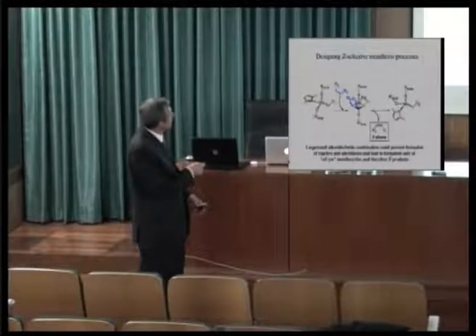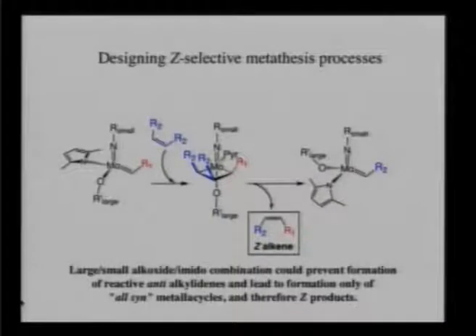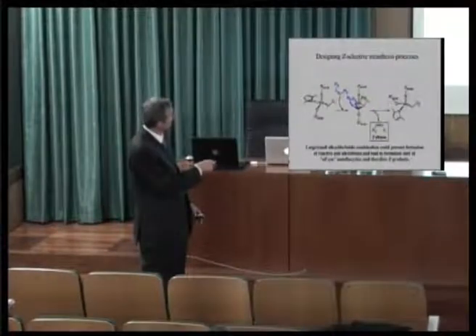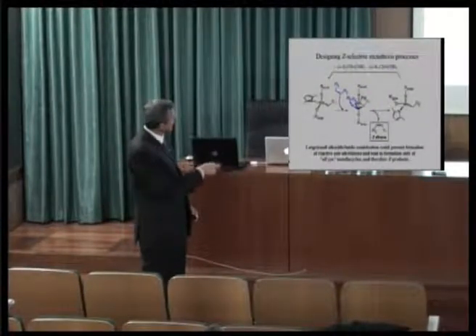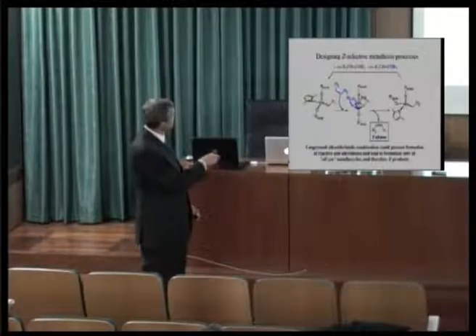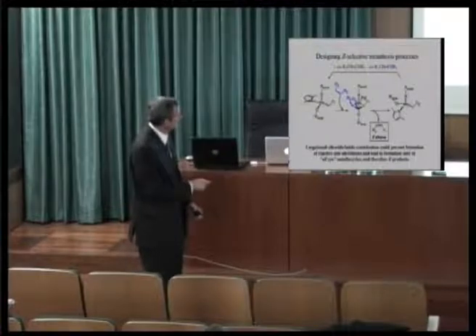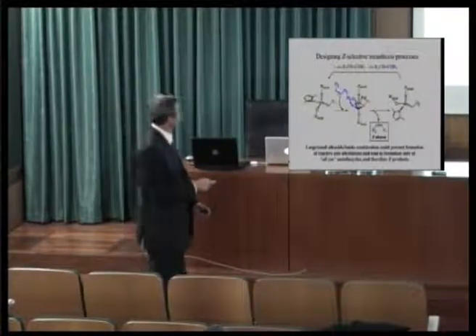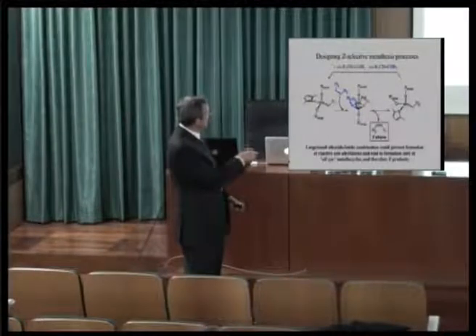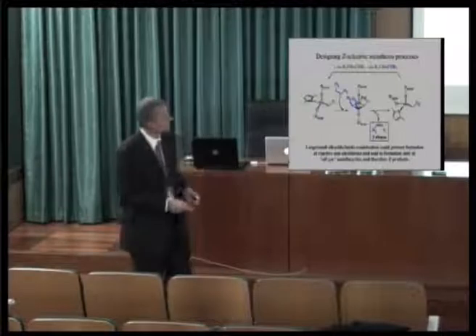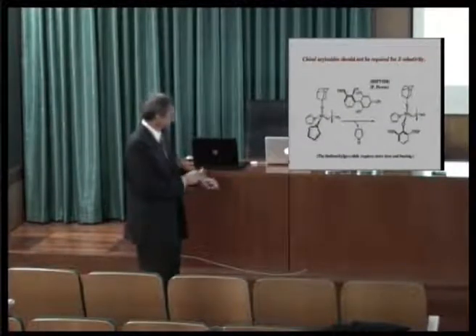That is, maybe what is happening here is you do form the same sort of intermediates in a substituted metallocycle, but they all have to point in one direction because this substituent is so large. There's no room to put any of these R groups down. And so the substrate comes in, you make this metallocycle, you make this product, which is Z. It has to be. You make this alkylidene, it reacts again to make this same Z product and go back here, and that's, in fact, the catalytic reaction, a Z selective reaction. So we thought maybe it's a large, small combination that's very important to give Z selectivity in these reactions.